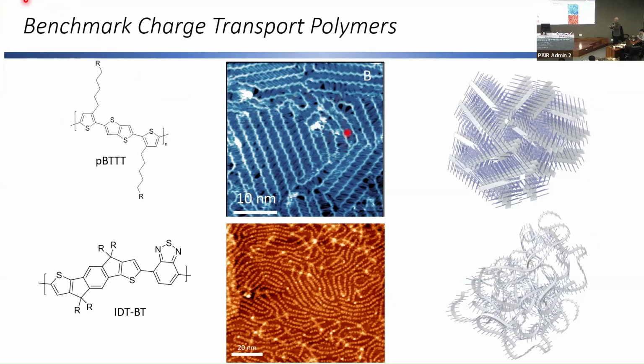We also did some STM imaging. And so this is a very high resolution STM. It's formed on a monolayer on a gold surface by electrospray. And here you can see, actually the best is probably to look up in the top corner here. The very light line here, that's the polymer backbone. And you can see the side chains here also beautifully interdigitated here. And this is this beautiful lamella.